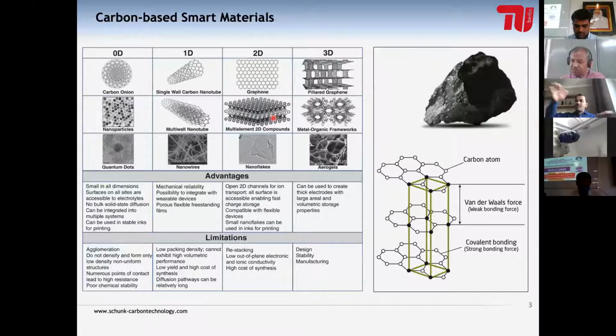And in two-dimensional graphene, we generally see problems with restacking. Once you exfoliate the material, these materials start restacking first. But sometimes it's really hard to get single sheets out of the graphene as well. And in three-dimensional material, there are some problems regarding design, stability, and manufacturing. Design means how would you design these materials? Second is stability, chemical stability I'm talking about, and manufacturing, because these are complicated procedures which we need to follow when we think to synthesize this material. But all of these problems can be solved using metal organic frameworks, which I will talk about in just another minute or so.